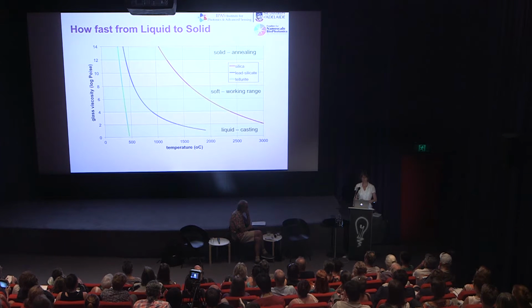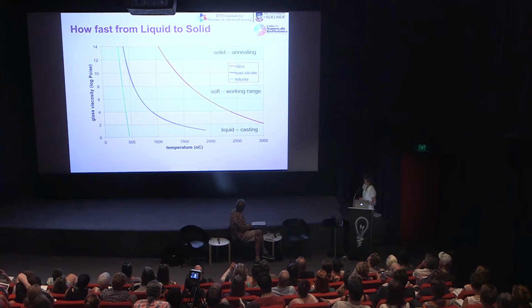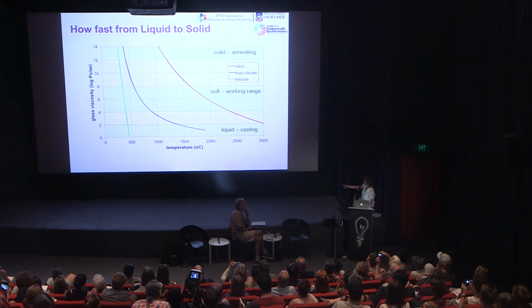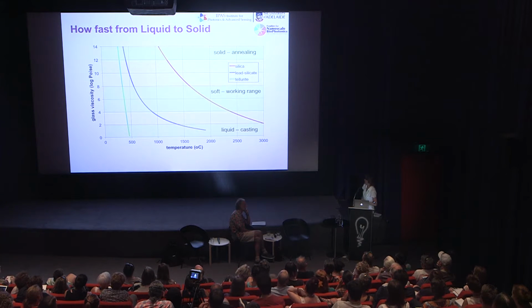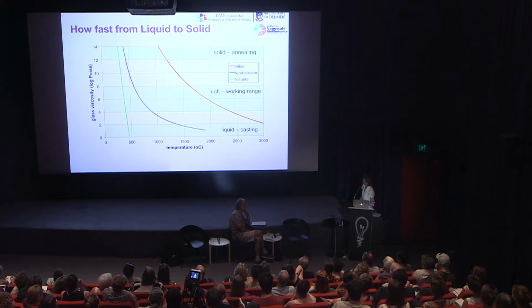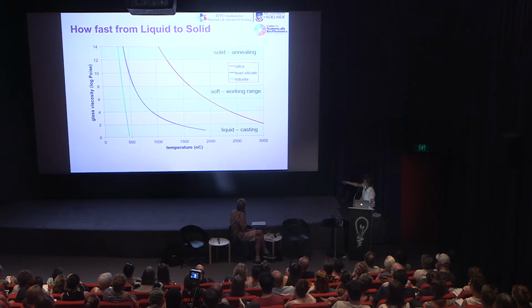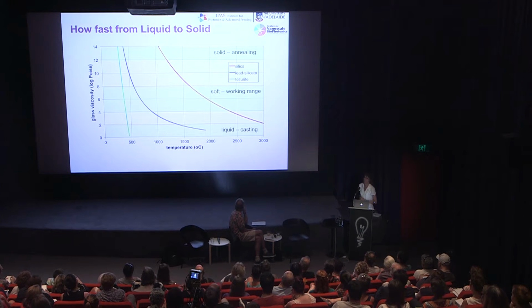So one very important property of glass is the viscosity. That is the change of the glass viscosity with temperature. Here I looked at important regions. This is a scale of the viscosity. If you have -2, this is the viscosity of water. And if you have the viscosity there, you have a value of 14, and this is really a solid. So you can see that the glass gradually changes the viscosity over this wide range of viscosities. Where we work in terms of extrusion and fiber drawing, and blowing glass and doing all sorts of unimaginable things with the glass, this is the soft glass or the working range. And then down here you have the range where you can cast glass.